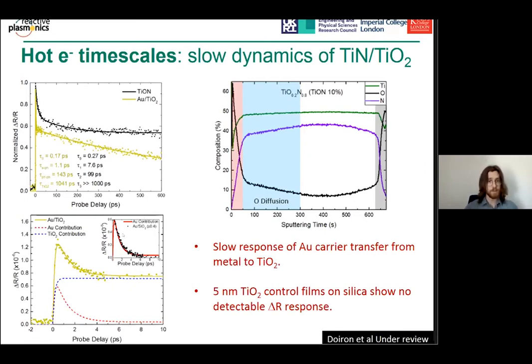So if we look at it, we compared gold and titania films with titanium nitride, and we see that gold films deposited on titania, so titanium dioxide, also exhibit this long lifetime. So what we're seeing is hot carrier generation in the gold, and then pumping into the titanium. And this is what we attribute to the long lifetimes in titanium oxynitride as well, because we completed SIMS measurements, secondary ion mass spectrometry measurements, which show that the interface in the titanium nitride films is a titanium oxide interface. So that explains the slow response of the titanium oxynitride thin films here.